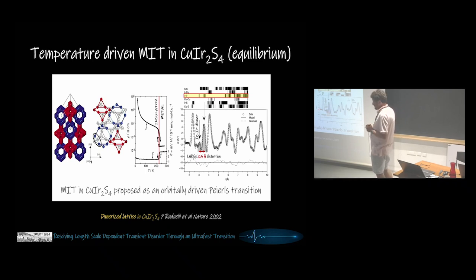So it has a metal-insulator transition on cooling, where your system goes from the high-temperature spinel cubic structure to a triclinic dimerized, spin-singlet dimerized state. And that actually has a very strong response in the structure. So this is a PDF, actually a neutron PDF, published some 25 years ago. The distortion is half an angstrom large.